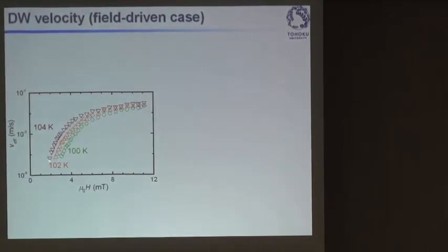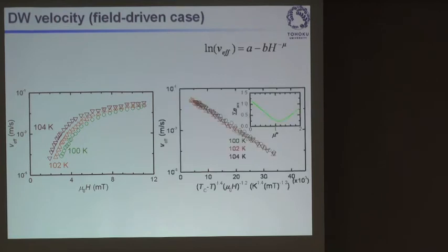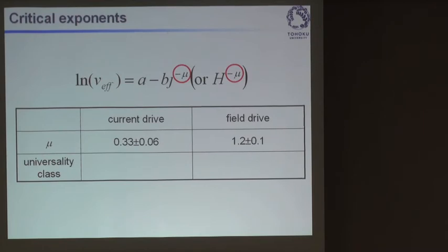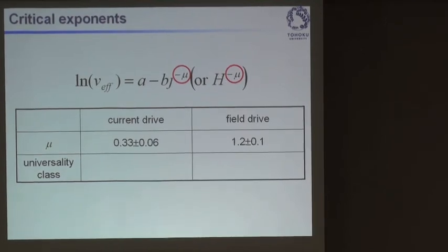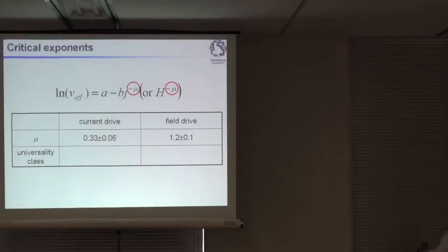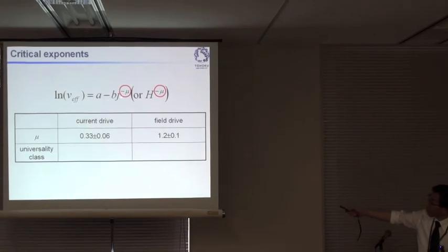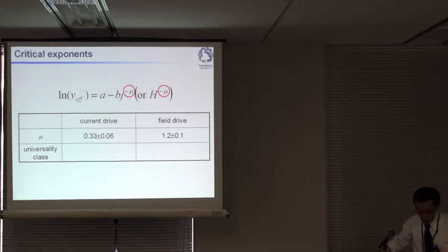We have applied magnetic field, and this is the velocity. Again, the velocity is exponentially dependent on magnetic field. Again, we use this form to identify the critical exponent characterizing the physics here. And we have found that the critical exponent is 1.2. So to our surprise, these two exponents were different. Here we have used the same gallium manganese arsenide, and we have used current to induce creep motion of the domain wall. We also used magnetic field to induce the creep motion of the domain wall. In the current driven case, the critical exponent was 0.33, and in the field driven case, the critical exponent was 1.2.